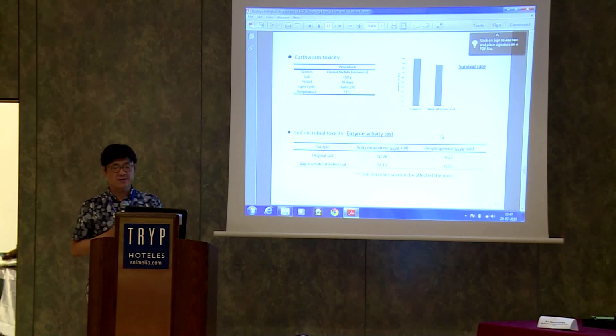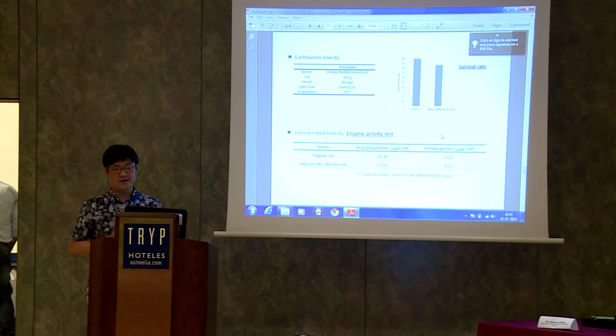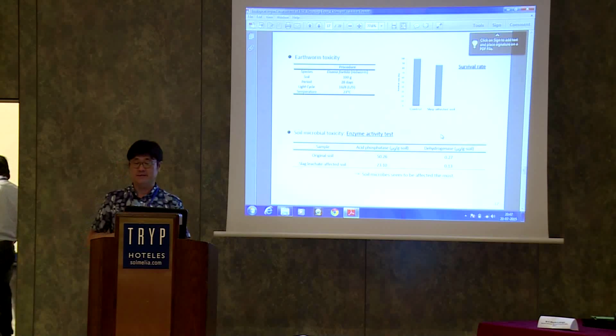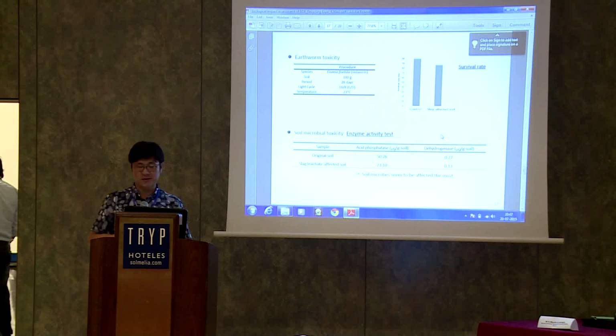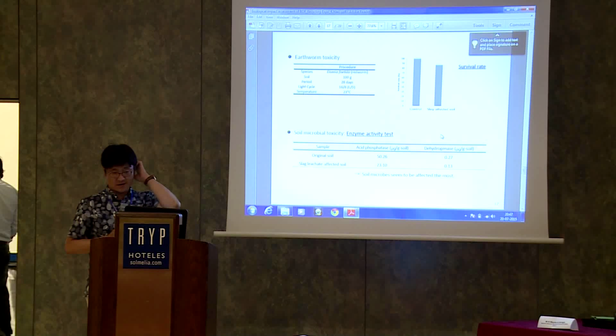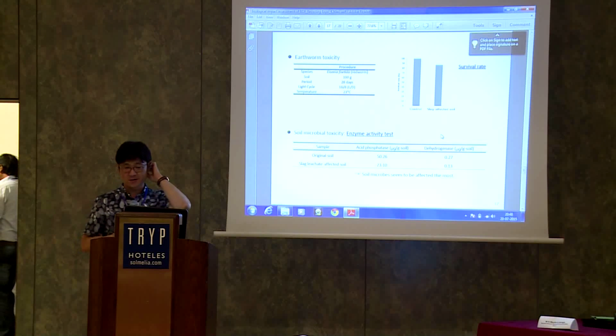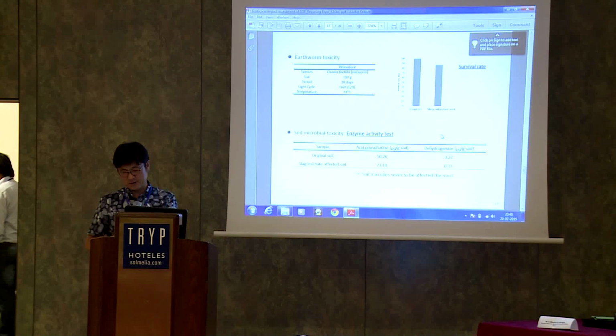And in terms of microbial toxicity, we did the enzymatic activity test, and we tested 2 methods: acid phosphatase activity and dehydrogenase activity. Compared to the original soil, the activity decreased by about half in the leachate-affected soil, which means, at least from this experiment, the soil microbes seem to be the most affected by the slag.